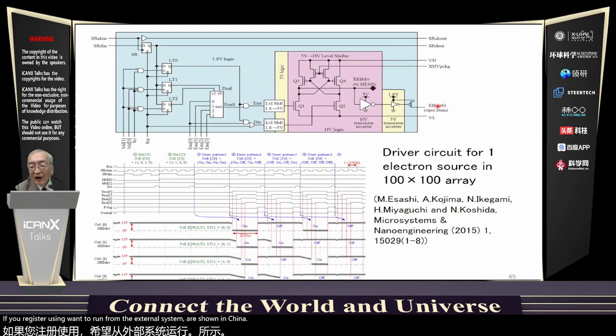The LSI for the active matrix control was fabricated through a 0.18 micrometer CMOS high voltage process. The circuit for one driver cell is shown in the upper part. The LSI shifts in bitmap data and the emitter is driven at up to 15 volts. The LSI operations were successfully confirmed, as shown in the lower part of this slide.